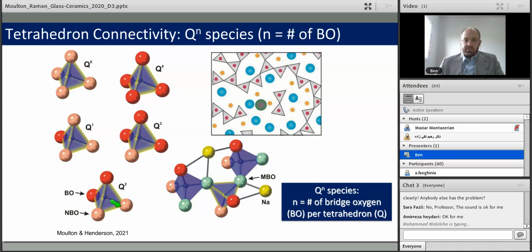If we look at the bottom of the screen here in the Q2 species, there are two types of oxygen, a red one and a pink one here, or flesh tone. The red oxygens are bridging oxygens, so you would picture another tetrahedron bound here and another tetrahedron bound here. And these are non-bridging oxygens, so they're not linked to another tetrahedron. So they would be surrounded by the modifiers. These oxygens having a negative charge of about 1, they need an alkali, or two of them need an alkali earth, to maintain charge balance.